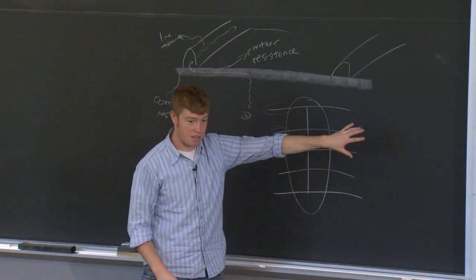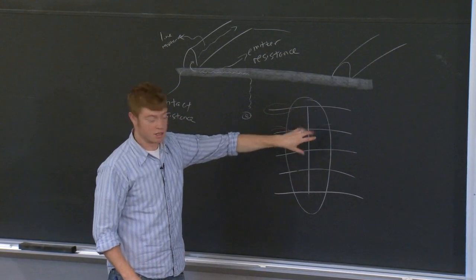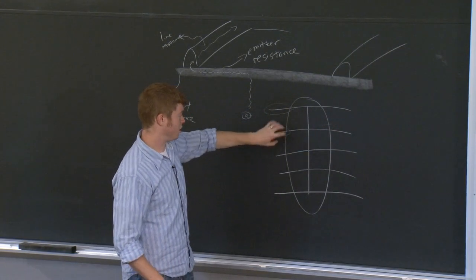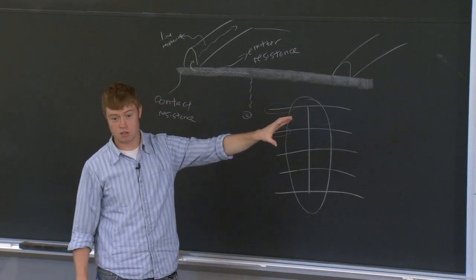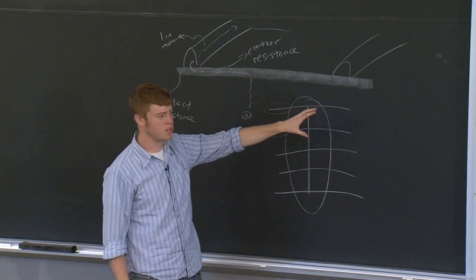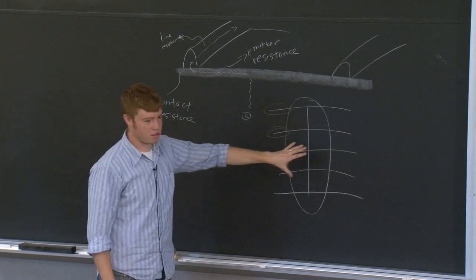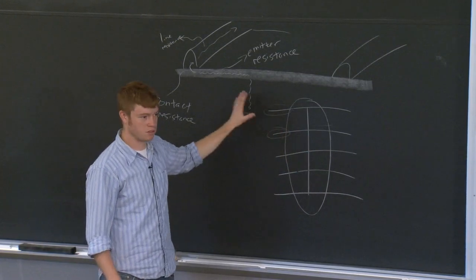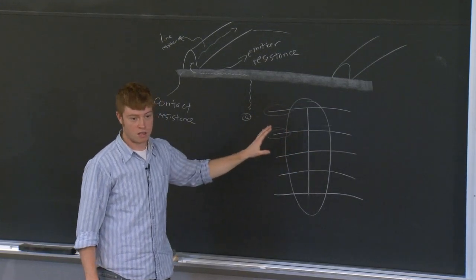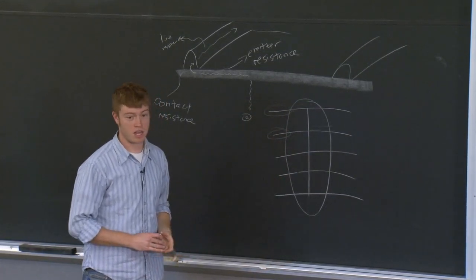Because when I fired at higher temperatures, I was getting shunting, and that was due to shunting through the center area. So I think that the RTA that I was using, this wasn't the case on some of the earlier cells I had processed, is rather inhomogeneous in terms of the temperature profile it's delivering to our cells. So I think that could be part of our problem as well.